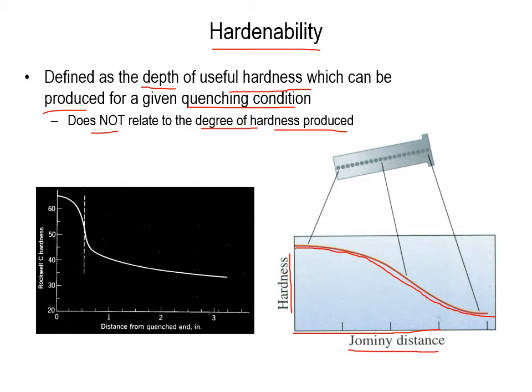If we look at this on a Rockwell C hardness scale on our y-axis, and our distance from the quenched end in inches, we have a graph that looks like this. We start off with a nice steep slope as it drops off pretty quickly as we get up towards 3/4 of an inch or so away from the end, and then it levels out a little bit more from 3/4 of an inch on.